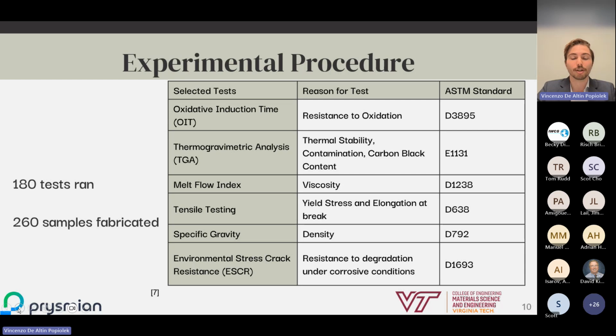For experimental procedure, we performed a variety of tests to compare our polymers and blends to industry standards. A few key tests are highlighted here. We performed oxidative induction time, or OIT, to test for resistance to oxidation. Thermogravimetric analysis, or TGA, to test for thermostability, contamination, and carbon black content. For thermal stability, we specifically checked to ensure that no degradation was seen under 100 degrees Celsius to ensure that this was an appropriate aging temperature for our thermal aging.